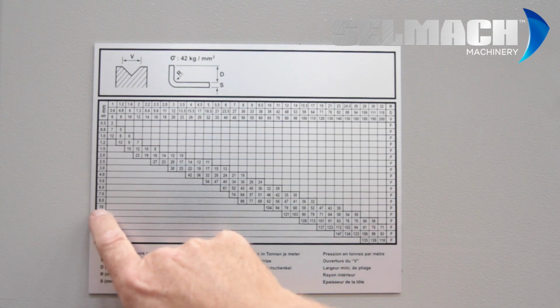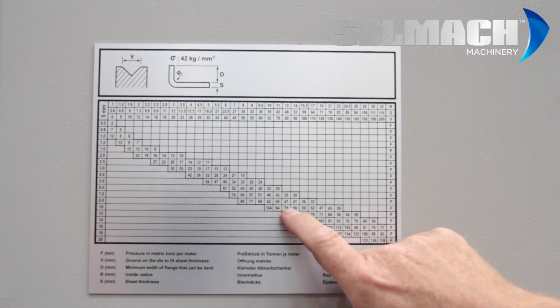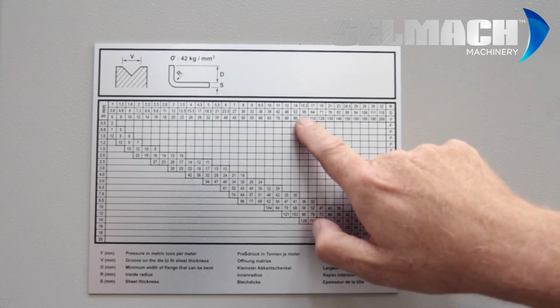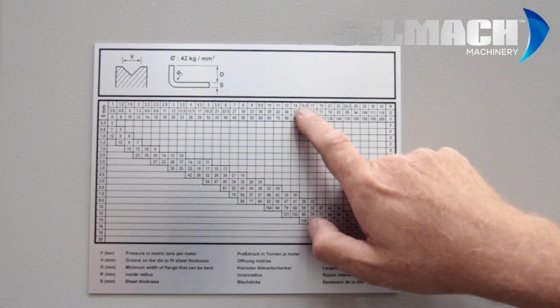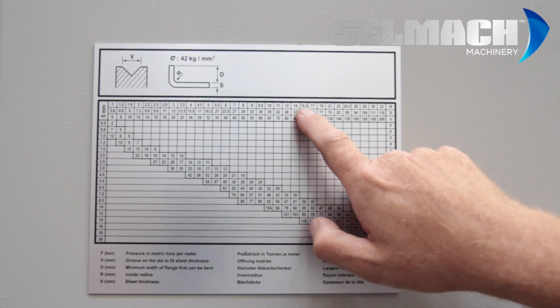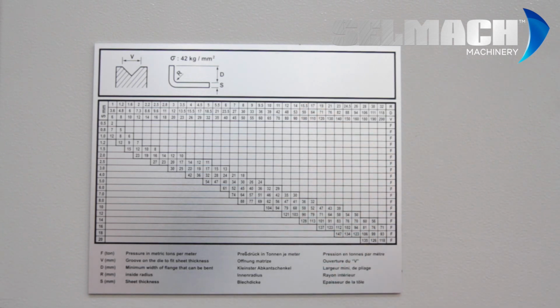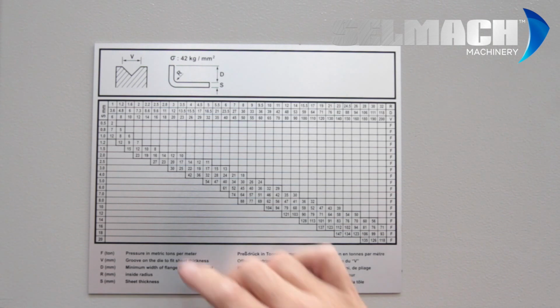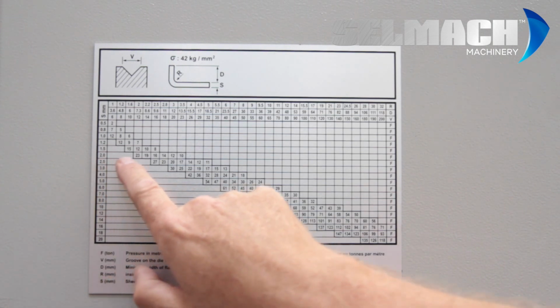10 millimeter material followed across to 100 mil V shows that the inside radius will be 15.5. So if your top tool had the exact 15.5 radius, when you fold it, it will come out without any marks, any denting, any cracks in the steel. It will be perfect.